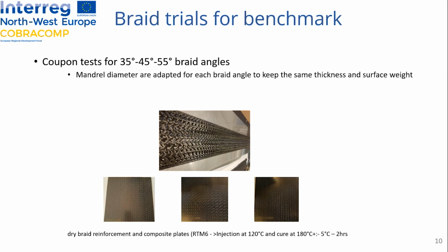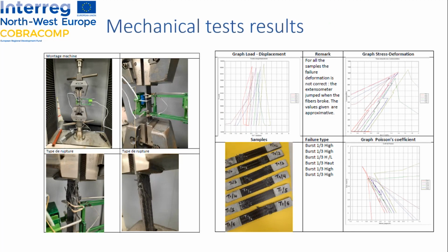A few words about the RTM injection. It is made using RTM6 resin with an injection temperature of 120 degrees, and a post-cure at 180 degrees during 2 hours. After the cure steps, we made a visual control to check that the composite plate is good. After that, all these plates have to be cut following the testing plan.